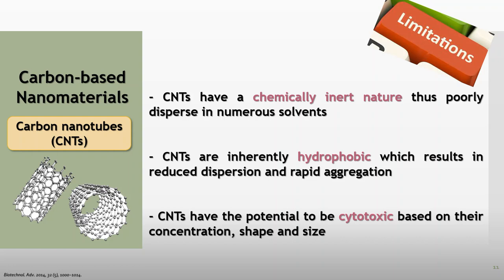A major complication of CNTs is their poor dispersion in numerous solvents due to their chemically inert nature. CNTs are also hydrophobic, which causes reduced dispersion and rapid aggregation. They also have the potential to be cytotoxic depending on their concentration, shape, and size.